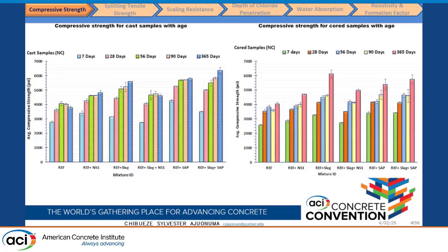For compressive strength, we tested at 7 days, 28 days, 56 days, 90 days, and 365 days. We had results both for the specimens cured in the lab under controlled conditions, and the cores extracted from the field. We noticed a gradual increase in compressive strength with age. For the mix with slag, there was a slight reduction in early age strength, but we also noticed an increase as the age of the concrete increases.